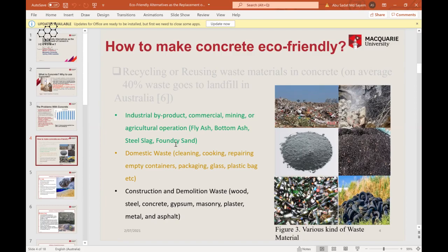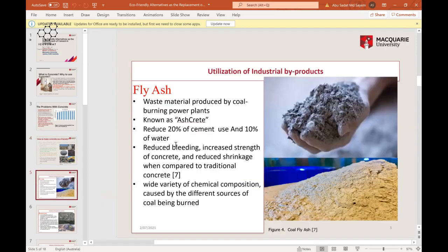In my first study, I focused on fly ash, and I found a good result. It is totally abundant from coal-burning power plants, and sometimes it is known as AshCrete. After studying this, I found that it can reduce cement consumption by around 20%, which can really help to get a better concrete and a better environmental impact. After using fly ash, I even found it reduced the amount of water used by 10%. Using fly ash in concrete also reduced bleeding, and it increased the strength.